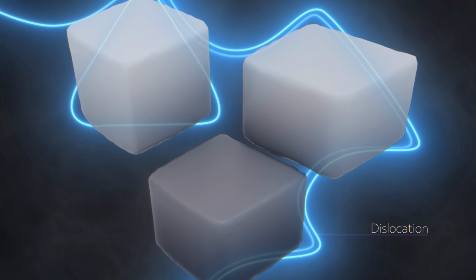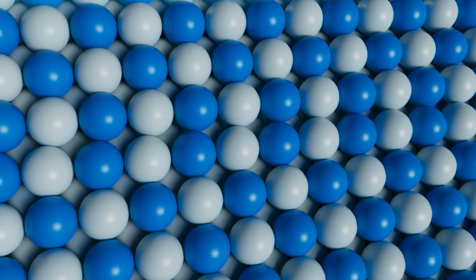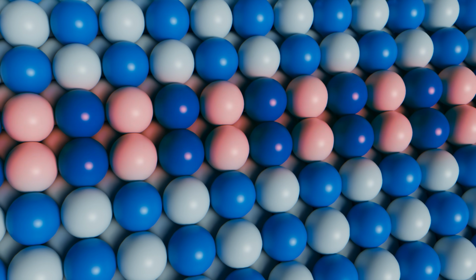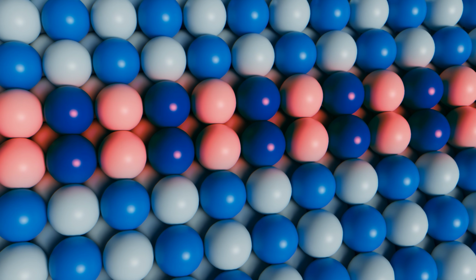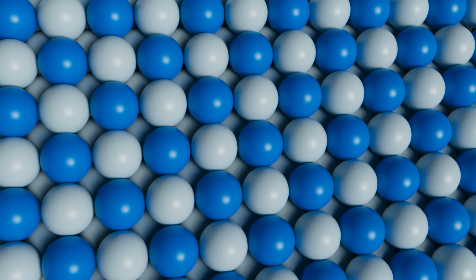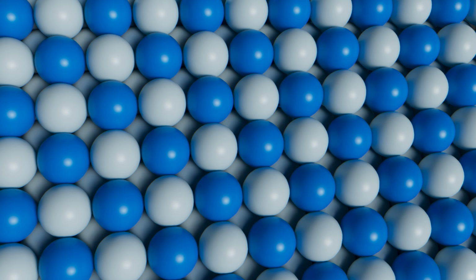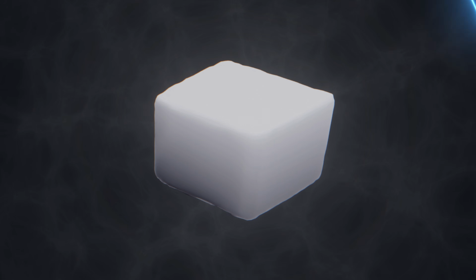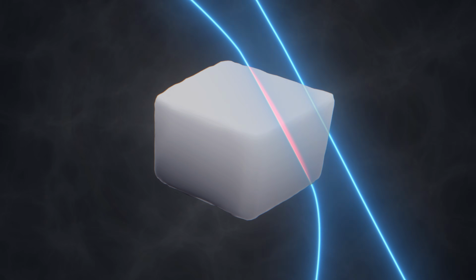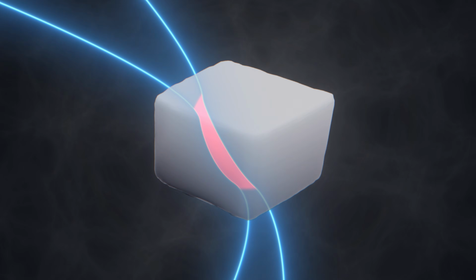But if you keep pushing and the stress gets high enough, a dislocation can finally force its way in. The catch is that this dislocation leaves the lattice in such a high energy mess that the only way it can keep moving is if there's a second one right behind it that puts things back in order. So in the gamma prime phase, dislocations have to travel in pairs, called super dislocations. I need that creation of those super dislocations, and I need that very high stress to be able to shear. So that's why the strength is very high relative to other alloys.